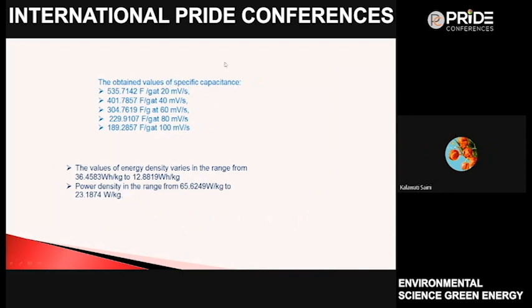When we compare the results regarding zinc oxide with Ficus bengalensis and Tabernaemontana, then we see higher capacitances are obtained with respect to these particles, and the energy density as well as power density are very much higher than with the banyan tree. It means the zinc oxide synthesized with Tabernaemontana is a better material for making the modified electrode or for battery storage.